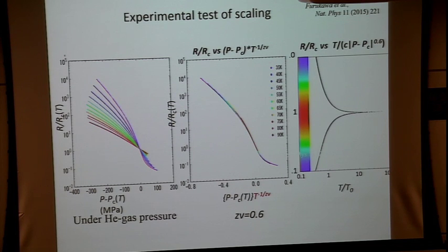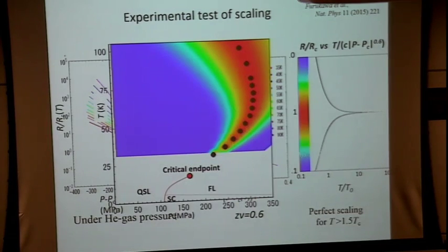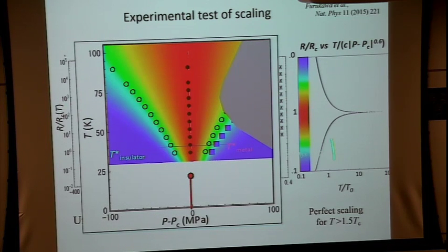So this shows that the quantum critical characteristics emerge in the high temperature region of this Mott transition. And this is a color plot. The color means the value of the reduced resistance, the normalized resistance. So this colored region is a quantum critical region. This blue region is a very good insulator. It's a middle region here. If this crossover line is converted to a vertical line, this phase diagram looks like this one. It's a nearly perfect mirror reflection, as expected for quantum critical transport.